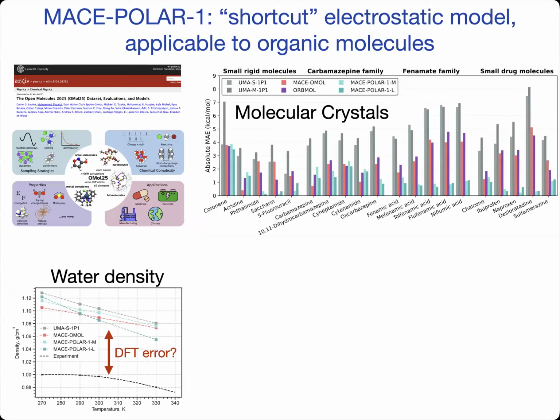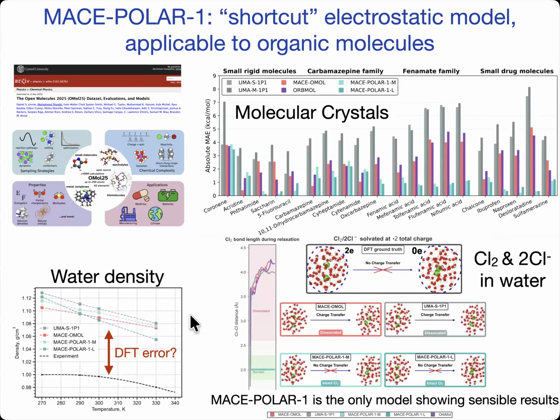Another very stringent test is bulk water density. And remember, this model is only trained on clusters, including water clusters, and its density, at room temperature and pressure, is about 1.08 grams. It's 8% too dense. And that is a very generic result. Every organic liquid is too dense with all of these models. So UMA is the model that's trained by Facebook, MACE OMol is a non-electrostatic model, and MACE Polar is the electrostatic model that we made. They all overestimate densities, and this is the consensus, although it's very hard to prove, but the consensus is that this is the prediction from this functional, this omega B97M-V functional, which just gives you a water density, organic density, that's too high. But regardless, the polarizable model gives qualitatively the right result when other models don't.